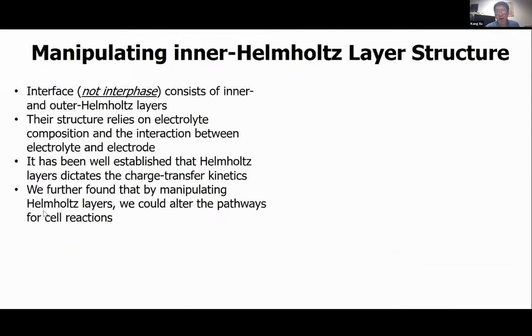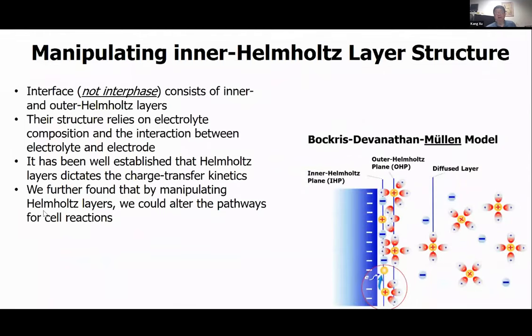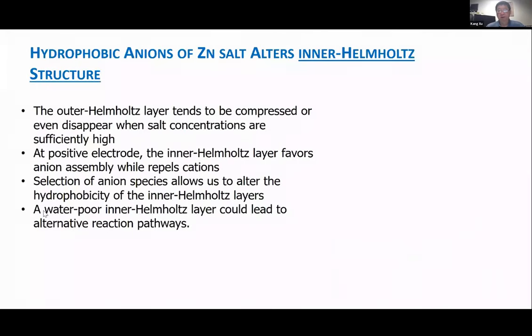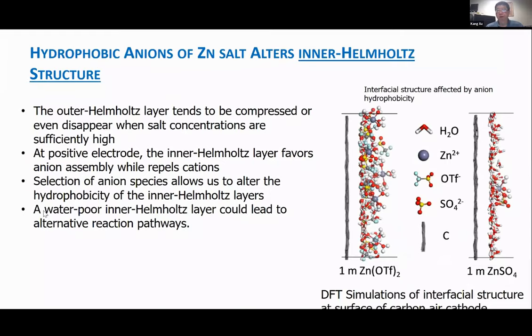We did this, I just mentioned, on the zinc anode before. On the cathode side, we found that it also plays a major role. I want to emphasize here that on the cathode side, we didn't find the interphase, which refers to the decomposition of the anion TFSI, which so far seems to happen only on the anode side. On the cathode side, we know that at the electrode surface, the inner Helmholtz layer dictates the charge transfer process. And in this special case, we found that we can even change the pathway of the cathode chemistry there. So one example we used here is the zinc salt, which has a very strong hydrophobic feature.